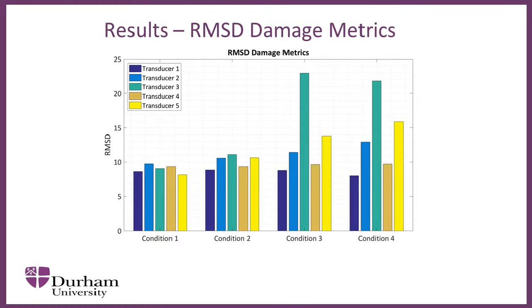In order to quantify the damage, a damage metric, RMSD, for each damage condition was computed for each transducer. The RMSD damage metric is the root mean square difference of the damaged impedance from the baseline over the frequency range analyzed. Where Re(Z1,i) is the impedance of the PZT measured under healthy conditions, Re(Z2,i) is the impedance for comparison with the baseline measurement at frequency interval i, and N is the total number of frequency points used in the comparison.